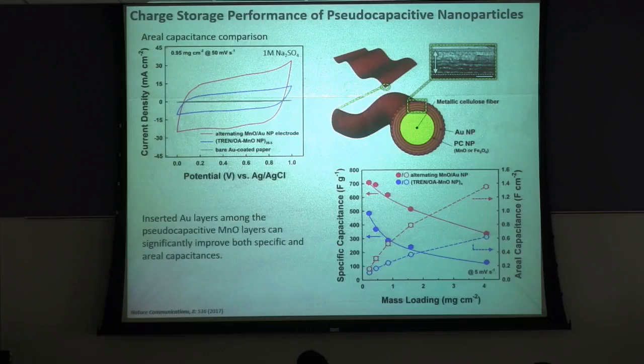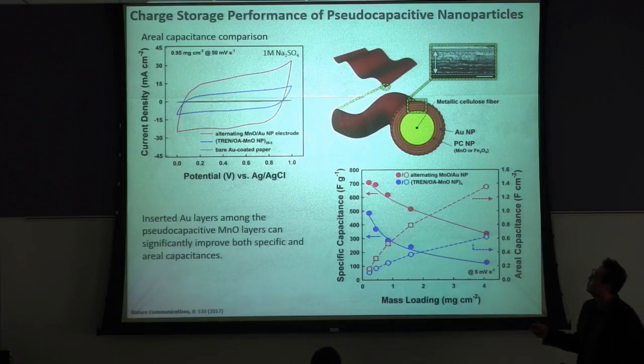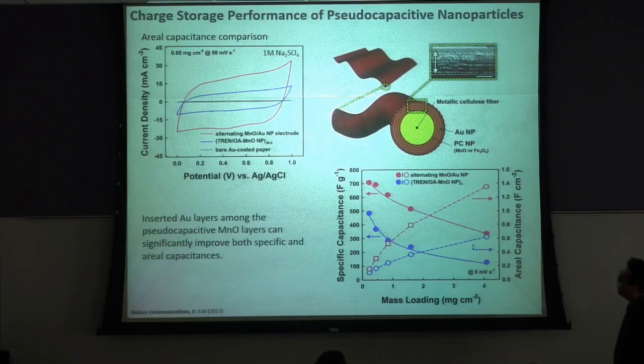Then on top of this conductive paper, we are incorporating manganese oxide and iron oxide nanoparticles. This gray one shows bare gold-coated paper, so just conductive, but there's no charge storage performance. After incorporating 20.5 bilayers of the manganese oxide, we can clearly see the increased charge storage capacitance. But one of the problems of this metal oxide nanoparticle is their poor electrical conductivity. So we periodically incorporate gold nanoparticles. For example, we deposit 3 layers of manganese oxide, then we incorporate 1 layer of gold. Then repeating again, 3 layers of manganese oxide, 1 layer of gold. So we are repeating this layer by layer deposition step.